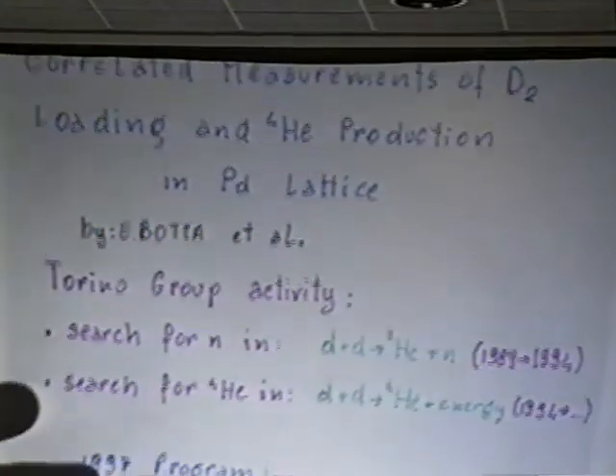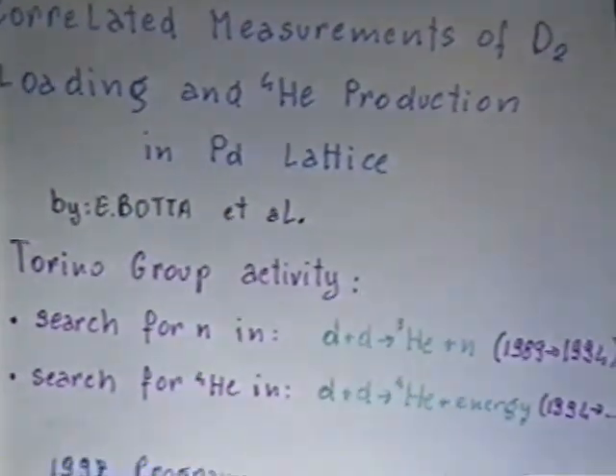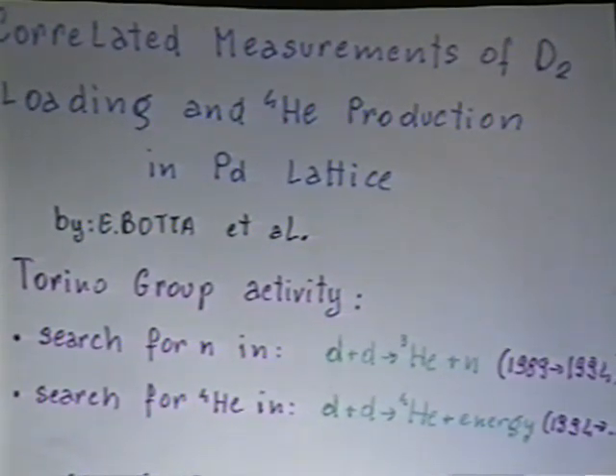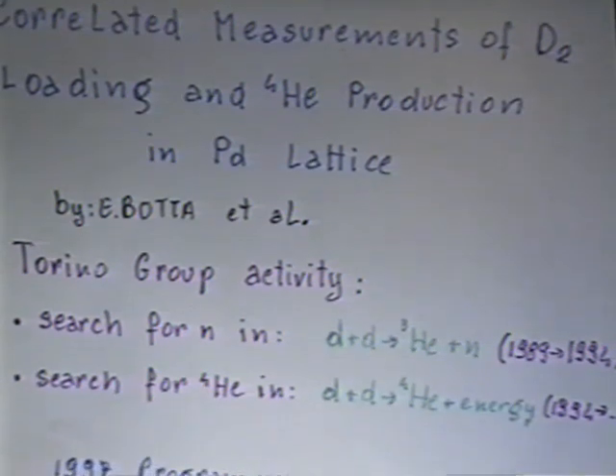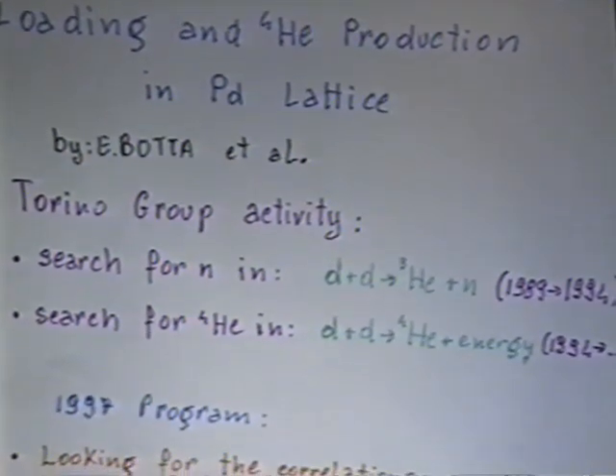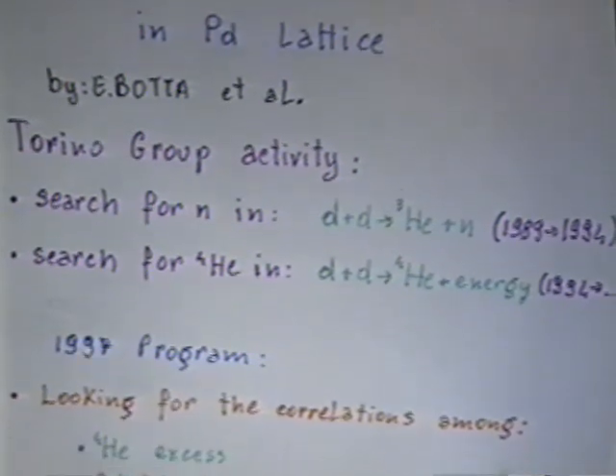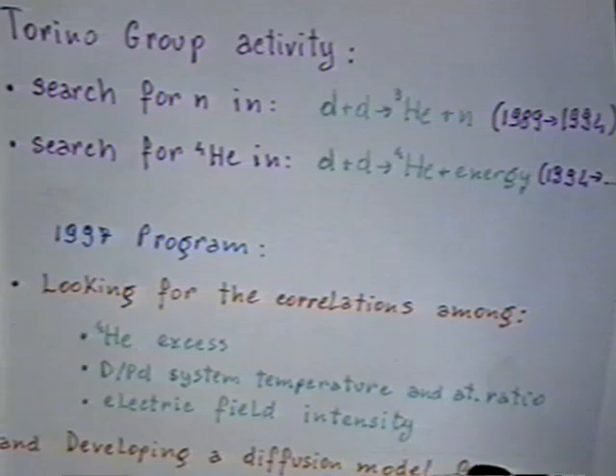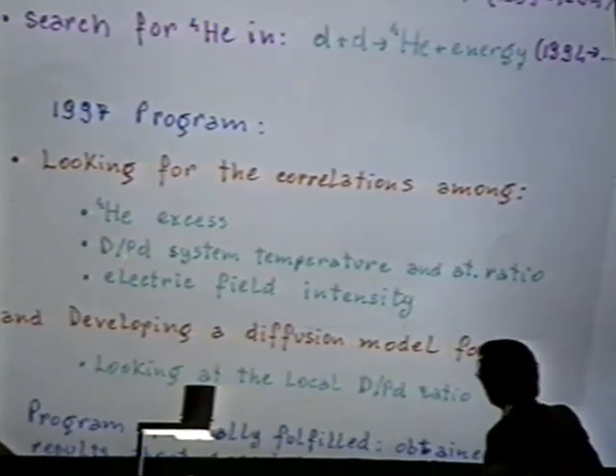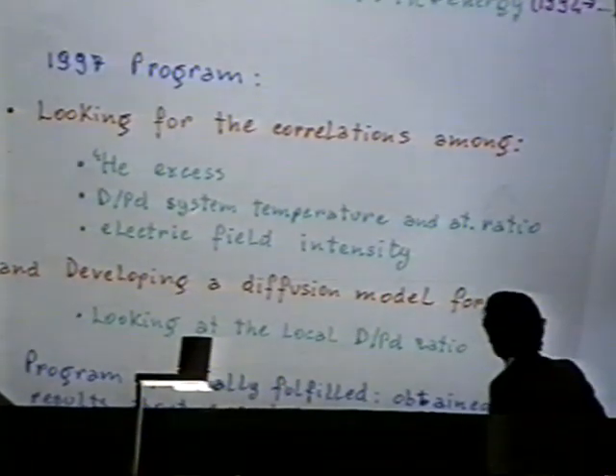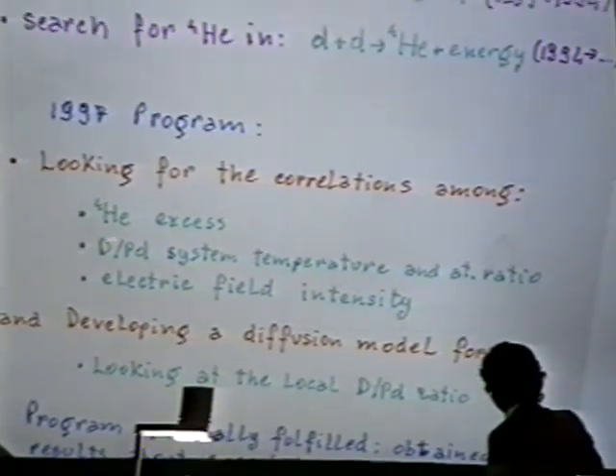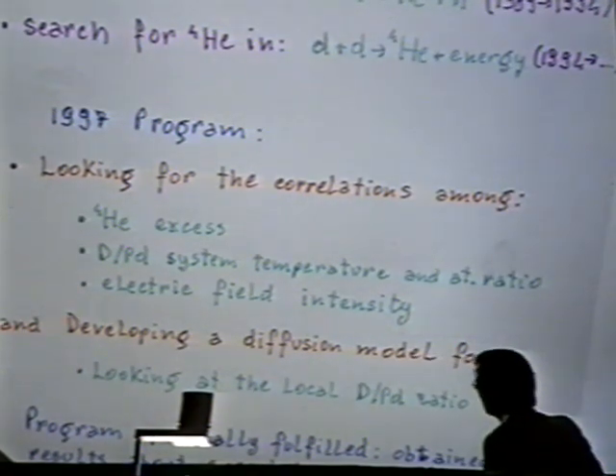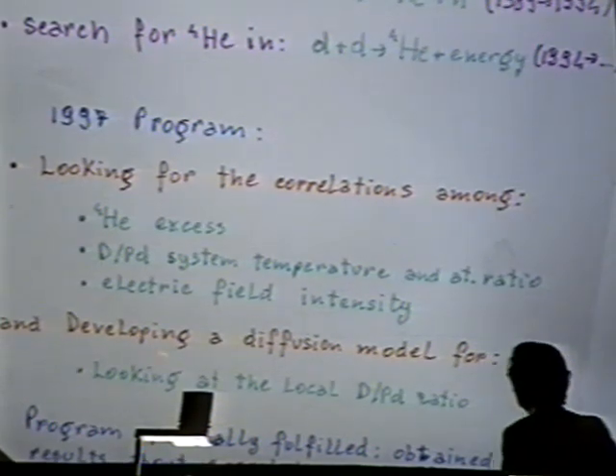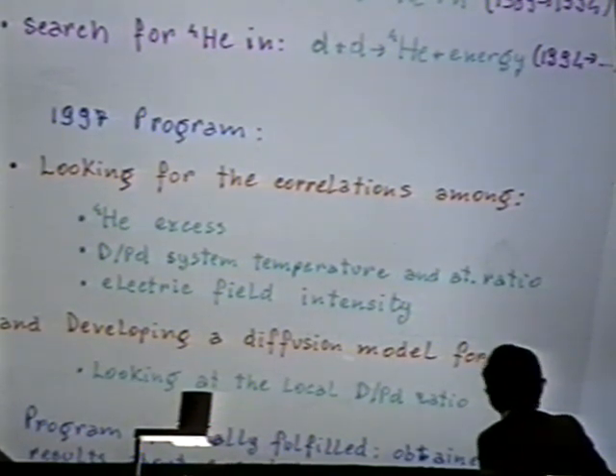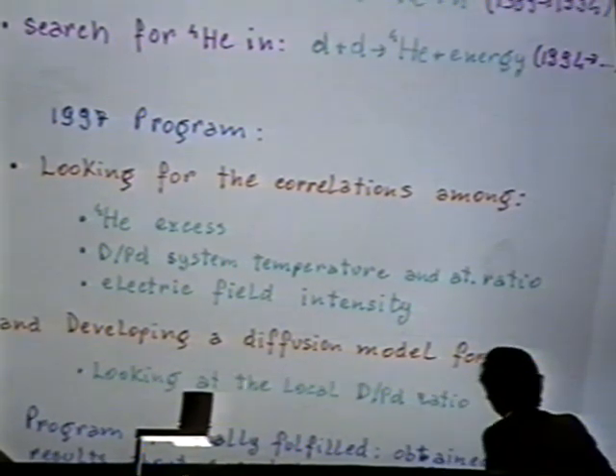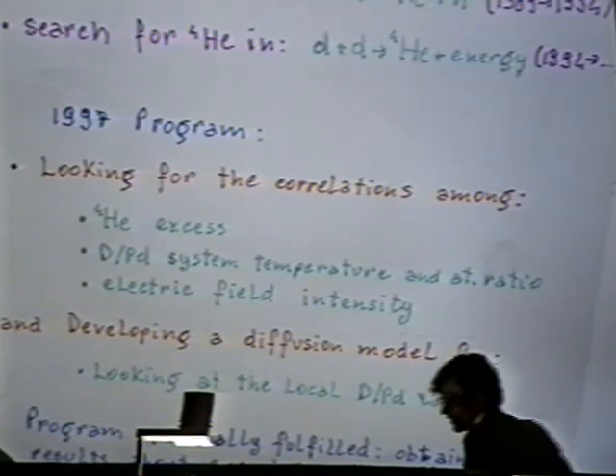The results concerning the helium excess were positive in 2 cases over 4 and were presented in the previous conferences. And starting from '97, we have tried to look at the correlation between helium excess and several parameters like temperature of the Pd system, the atomic ratio D over Pd, and the intensity of the applied electric field. Also, we are developing a diffusion model to look in some detail at the local concentration of the deuterium inside the matrix.